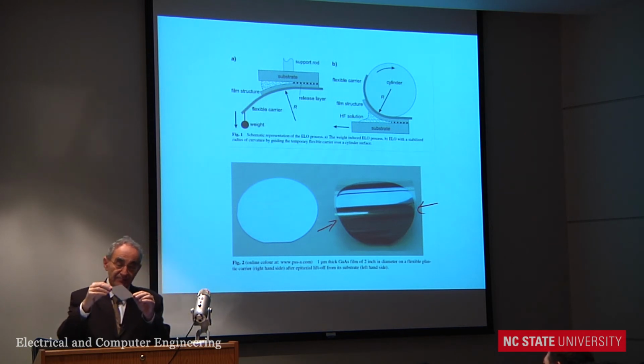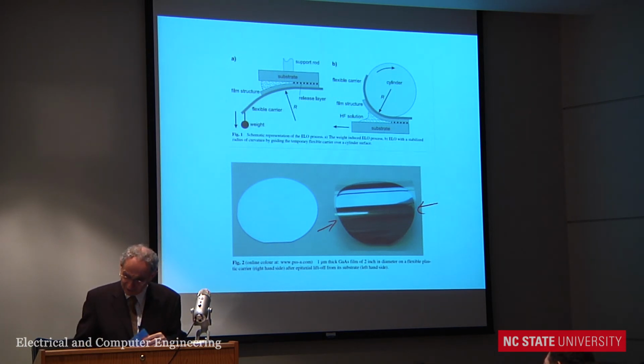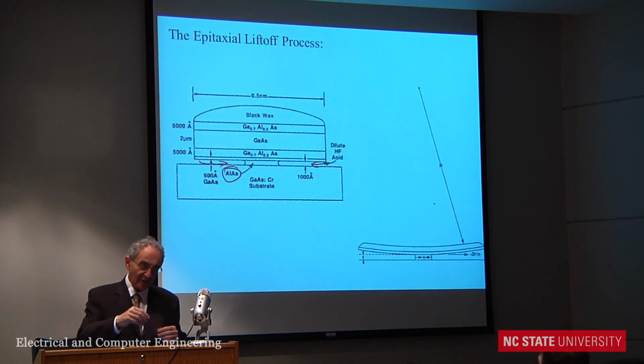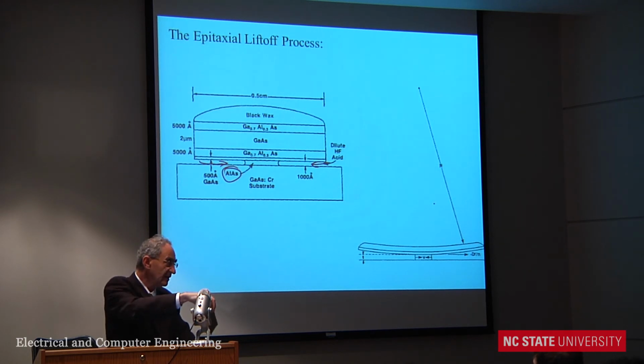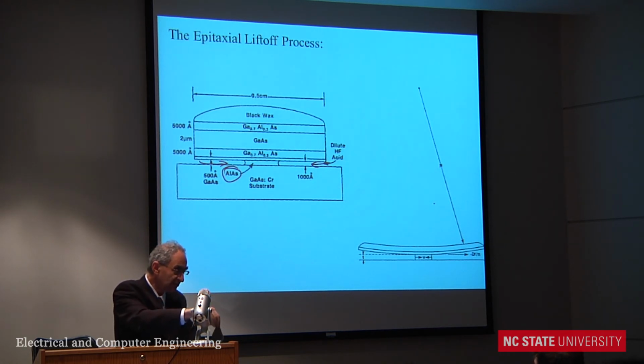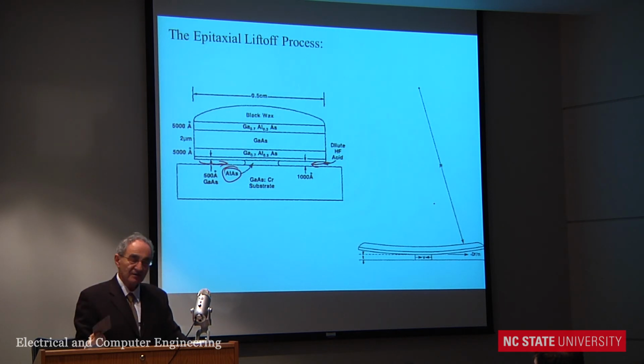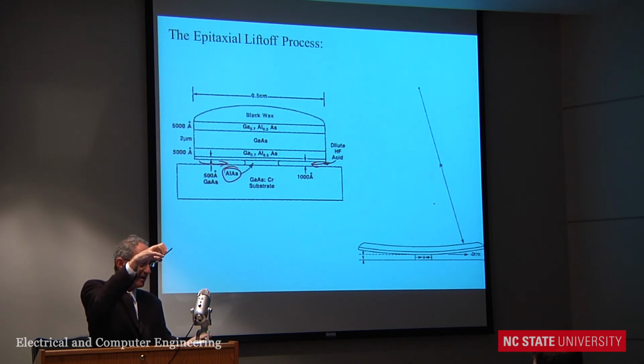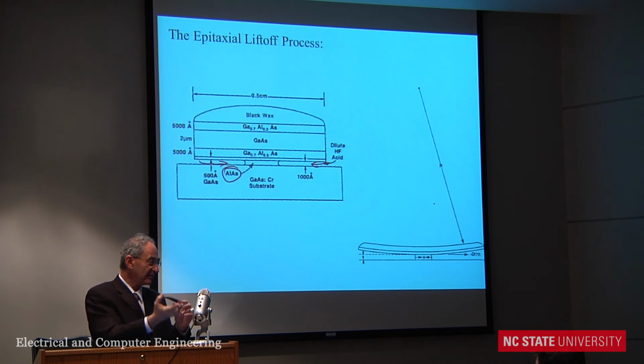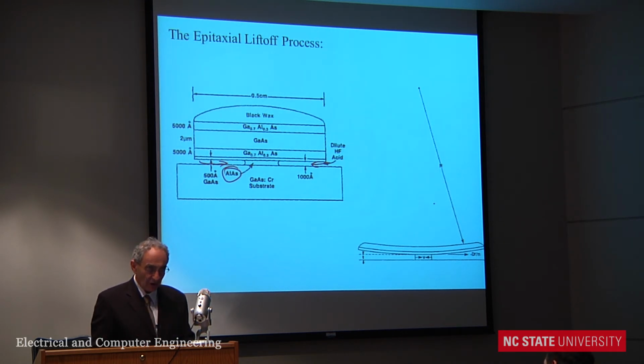What they do with the wafer is not done the way the Dutch showed it here. It's more like this. You have a cassette with 1,000 wafers. You dunk it into hydrofluoric acid. You come back in 2 hours. You take it out and rinse it, and it looks like nothing has changed. But actually, the entire underneath of the film has been undercut. And then they come along with a vacuum chuck, looking at the copper side, and they pull off the film. It's a freestanding thin film, just like this. So that's how complicated it is.